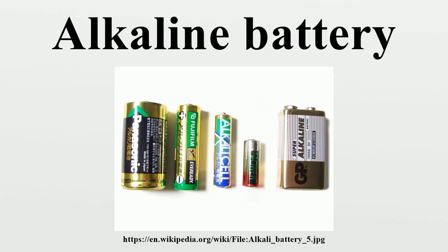Current. The amount of current an alkaline battery can deliver is roughly proportional to its physical size. This is a result of decreasing internal resistance as the internal surface area of the cell increases. A general rule of thumb is that an AA alkaline battery can deliver 700 mA without any significant heating. Larger cells, such as C and D cells, can deliver more current.